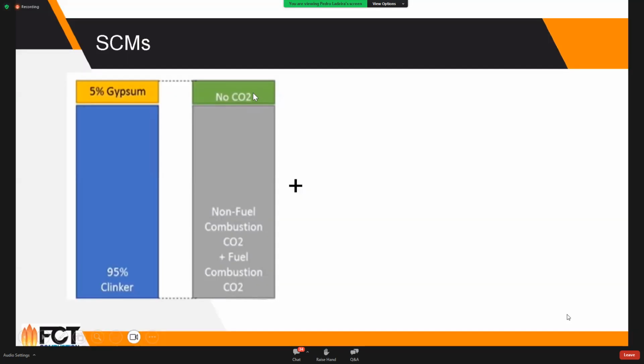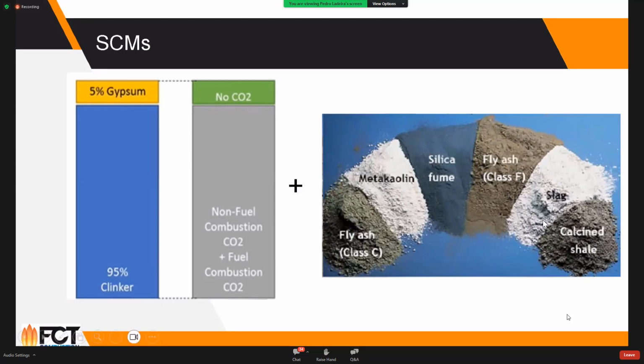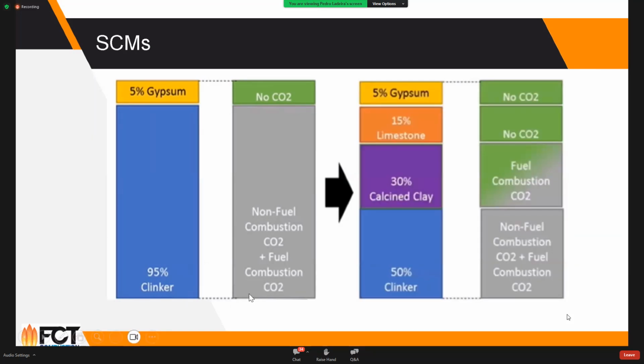We cannot really say no CO2 because there's a minor amount of CO2 being emitted for the fact that you are bringing in gypsum and you are mining it and so on. But again, you can use all sorts of substitute elements for the composition of cement, and if you do that, you can go from this configuration through something like 50% clinker, calcined clay, limestone, and gypsum. So here you really are relatively low to no CO2. Again, this one has less CO2 because it doesn't have the carbonation taking place. So all the CO2 will be reported as a fuel CO2 for this one, and the one coming originally from clinker. So you reduce the total amount of CO2.